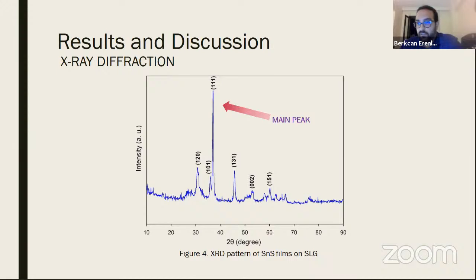X-ray diffraction section. The crystal structure of the tin sulfide thin film was measured using grazing incidence X-ray diffraction with a cobalt K alpha source, and the generator settings were 40 kilovolt and 40 milliampere, in the 2 theta angle range from 10 degrees to 90 degrees. As can be seen in figure 4, the XRD pattern of tin sulfide films on soda lime glass has a sharp main peak. You can see the 111 plane, and it is a good sign of film structure.